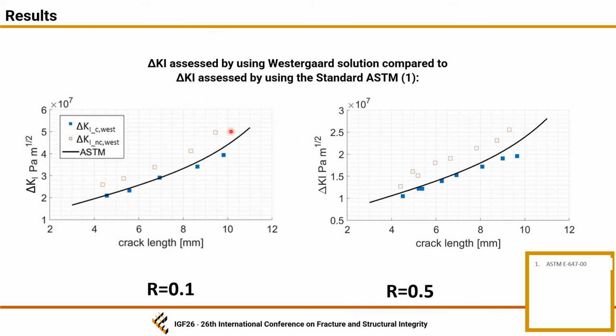In order to make more consistent considerations, in the following graph we can see the stress intensity factor assessed by using the Westergaard solution and the new formulation, and the Westergaard solution for the classic formulation, compared for both stress ratios to the stress intensity factor evaluated according to the standard. We can see that there is a great agreement between the data from the new formulation and those provided by the standard, with respect to the stress intensity factor assessed by classical theory not accounting for the mean stress effect.